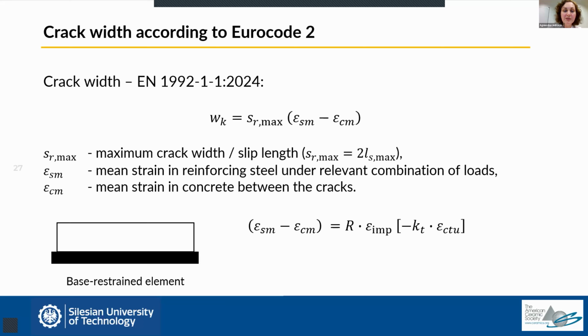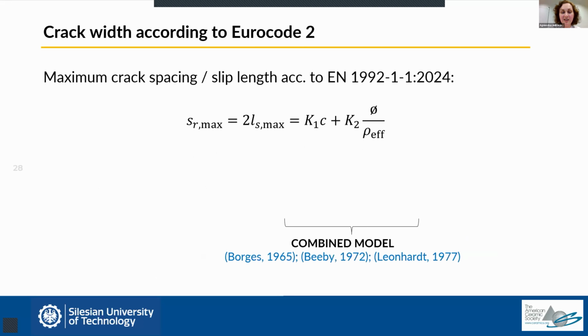However, this value is reduced by the so-called extensibility of concrete, which means the ability of concrete to extend between cracks. So bluntly speaking, we say that cracks happen, but then concrete can regain some of its volume between cracks as a form of relief of stresses. So this is an important factor to account for. However, as far as the crack spacing is concerned, Eurocode proposes to use the same approach as it does for direct loading.